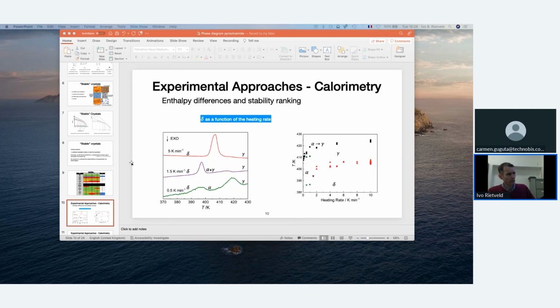Same story for heating beta, where you can have one peak, and there I show with X-ray diffraction that you actually get a mixture of delta and alpha. And this mixture of delta and alpha at a certain point will also transform into gamma. You can see that here very well. And after that, you always have the melting peak of the gamma form. So from that, you can see that gamma at a certain point will always form. Again, it is absolutely impossible to put a finger on the transition temperature, the equilibrium temperatures, but you will have an idea of how much enthalpy is involved with the different transitions by studying this very carefully and with different quantities.